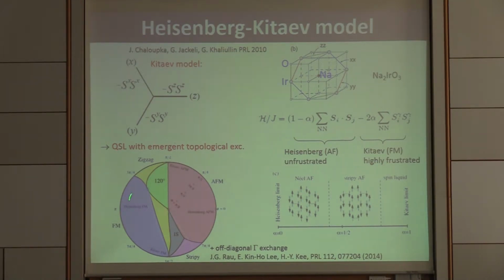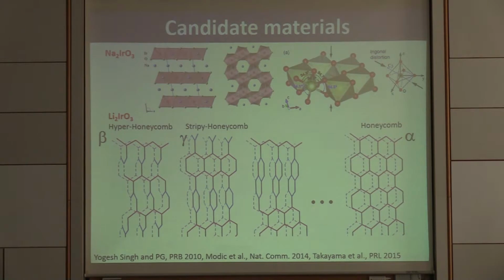So actually, if we also consider this off-diagonal exchange, we can get various different ground states, even incommensurate, non-coplanar ordered phases. And at the 2 poles of that diagram, we would have the Kitaev quantum spin liquid phases. Now, let me talk on these materials. So sodium iridate is a layered material where we have these iridium honeycomb planes, and in each plane we also have a sodium atom, and those planes are stacked along the z-axis by intervening hexagonal sodium planes.